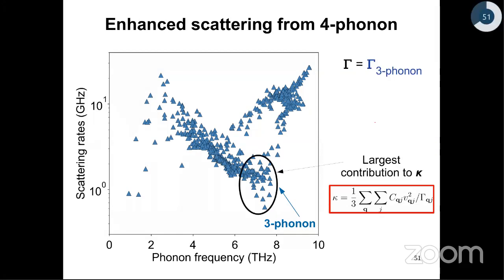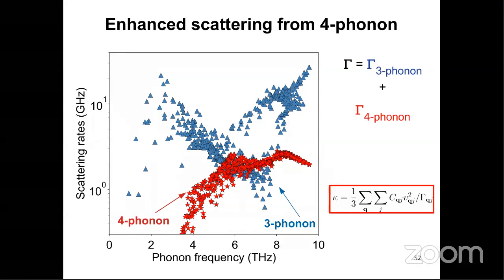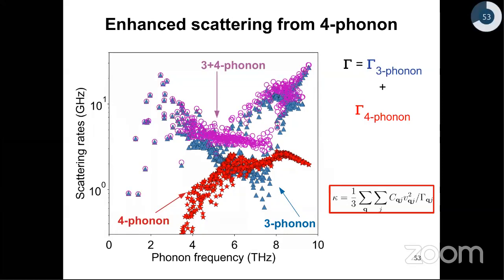So you can see that these phonons have very low 3-phonon scattering rates, and because scattering rates occur in the denominator, these phonons contribute the largest to the overall thermal conductivity with a 3-phonon picture. Now, if I add the 4-phonon scattering rates to this plot, you can see that 4-phonon scattering rates are the largest precisely in the frequency range where the 3-phonon scattering rates are weakest. So when you add these together through some kind of a Matthiessen's rule approach, you find that there is almost a 10-fold increase in the scattering rates at this lowest scattering rate point.